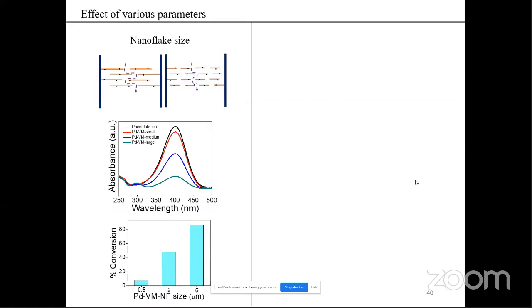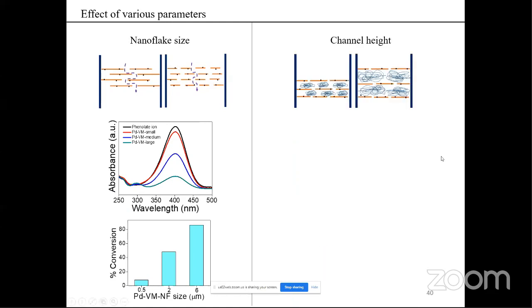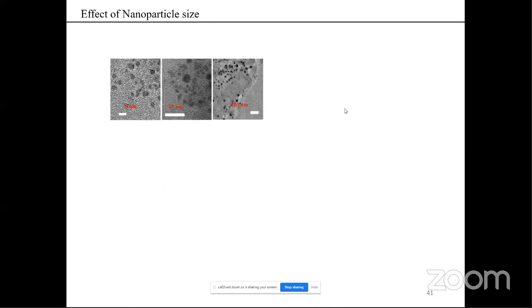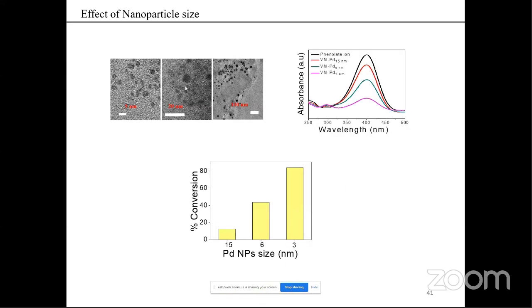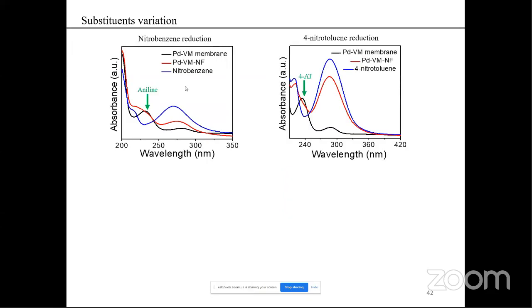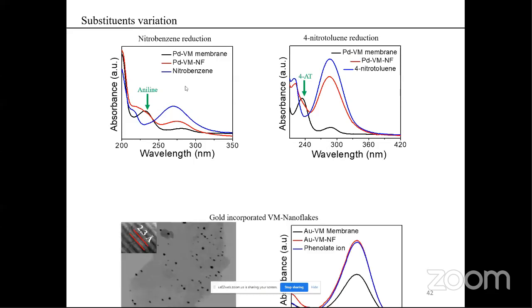So similarly, we can vary various parameters of the materials. For example, we can change the flake size, we can change the space between the channels to control the reaction conditions, and we can also change the nanoparticle or catalyst size, and depending upon all these parameters, we can vary the outcome of the reaction by changing the nanofluidic confinement. Similarly, we can do different reactions like nitrobenzenes, 4-nitrotoluenes, all these things also. That is, we can always see that confinement has a definite effect on the reaction kinetics.